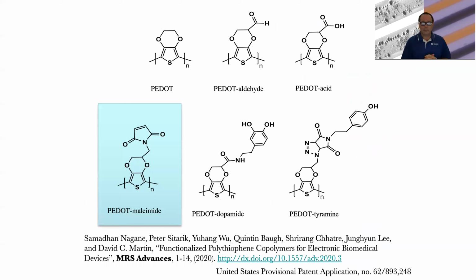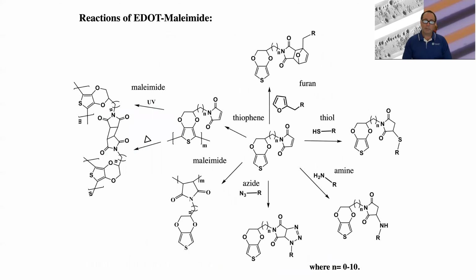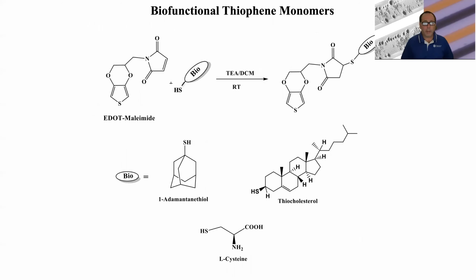So the most recent monomers are, again, different in the sense that we've made a PEDOT aldehyde, dopamide, and tyramine, but the real important one of all of these is this PEDOT maleimide. And so PEDOT maleimide is very interesting because if you've got maleimide, you've got access to a wide variety of different chemical reactions, either with furans, thiols, amines, azides, or polymerizing the maleimide or the thiophene itself. So you have a whole huge laundry list of chemical reactions that you can use to optimize.